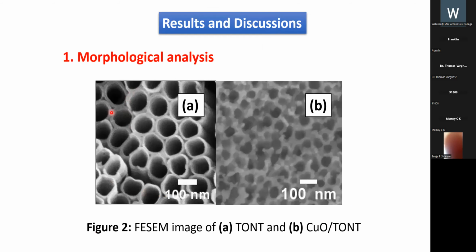Moving to the results and discussion. First, morphological analysis. The micrograph reveals a perfect tubular structure for the TONT. The surface morphology of the prepared CuO/TONT analyzed from FE-SEM indicates thickening of the boundary walls. However, the tubes are not blocked and the tubular structure is still retained.